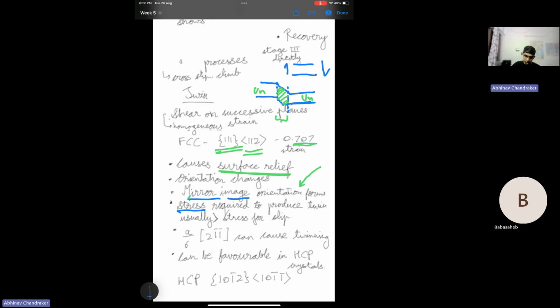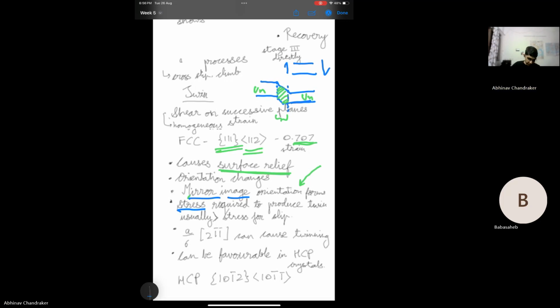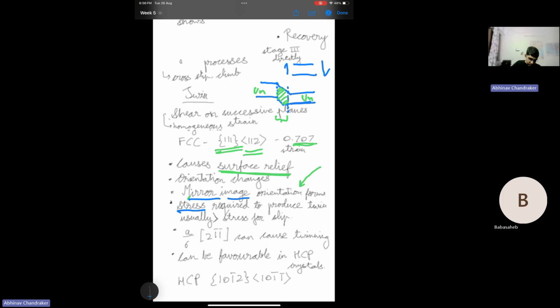Though the strain associated with twinning is quite high. Also, the exact mechanism of twin formation is still debatable. The CRSS for twinning is also debatable. We know the general trend that it is not so sensitive to temperature, unlike slip. It is not so sensitive to stresses.